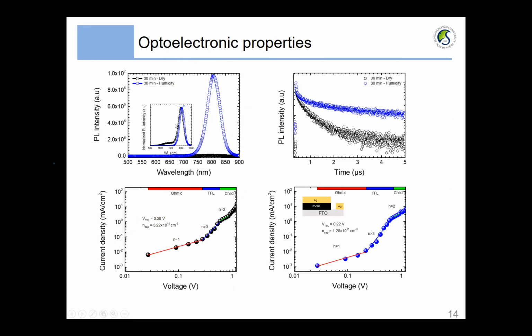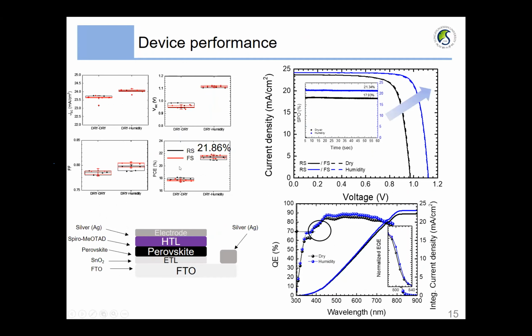We continued to check the PL emission with TRPL measurements. We found that the PL emission from the humidity condition was about 100-fold that of the dry condition. We also found that the humidity condition exhibits a longer carrier lifetime with a lower trap density. And we were able to achieve a 21.86% PCE with negligible hysteresis, along with a noticeable improvement of the open-circuit voltage and the short-circuit current, which resulted from the lower trap density.